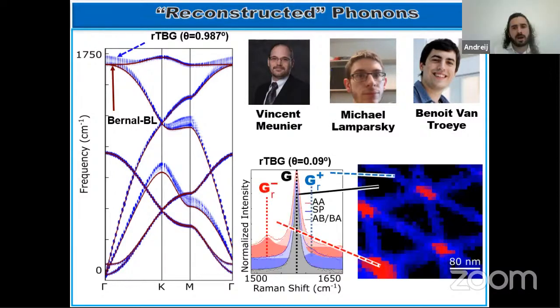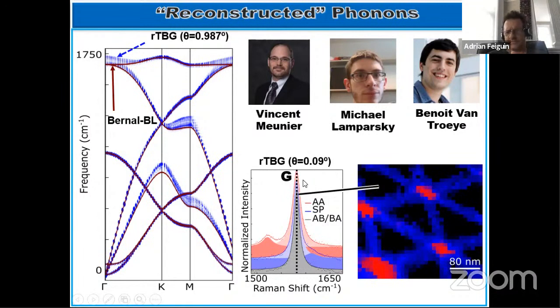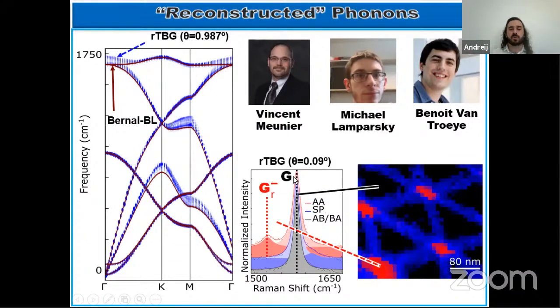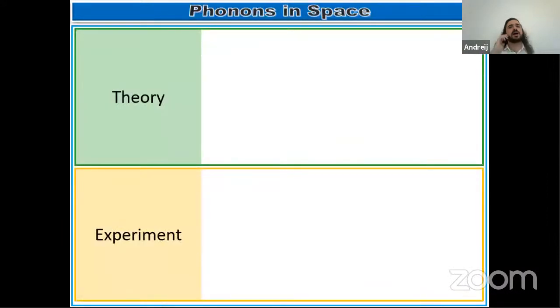Okay, so on the experimental side, we saw a single Lorentzian G peak at the ABBA sites, while at the AA site we observed a new peak at the left of the G peak, which we call GR minus, and at the SP site we observed another new peak at the right of the G band, which we call GR plus. Okay, so there is some similarity between these experimental peaks and what the theorists observed in their diagram.